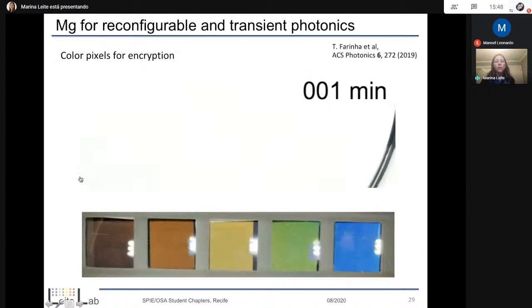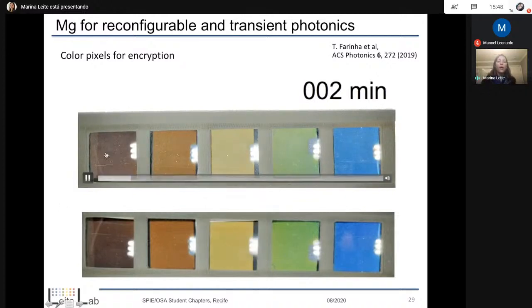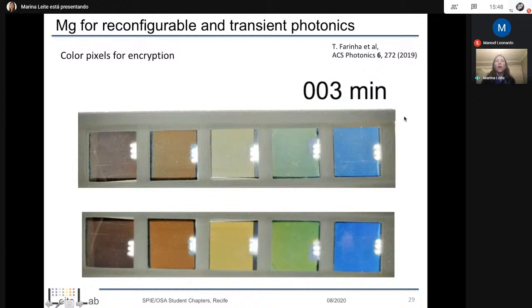So what we did was to first demonstrate that we can actually use those for encryption. Essentially, what I'm showing you now is a video where we put these color pixels in water. Magnesium dissolves in water, and one of the byproducts is magnesium hydroxide. MgO also dissolves in water to magnesium hydroxide as well.